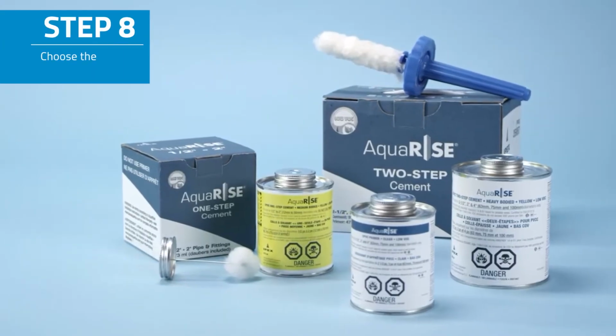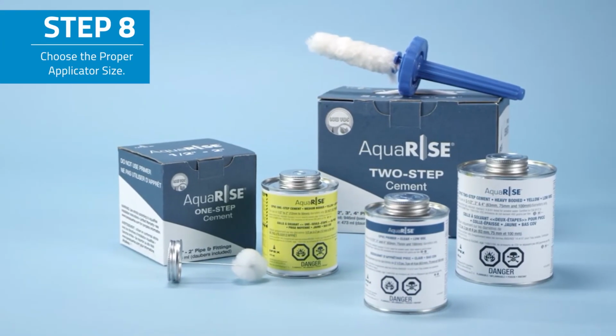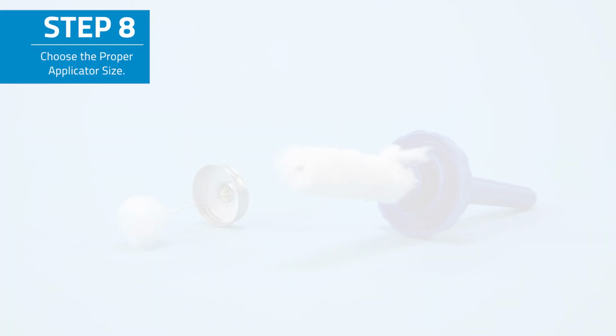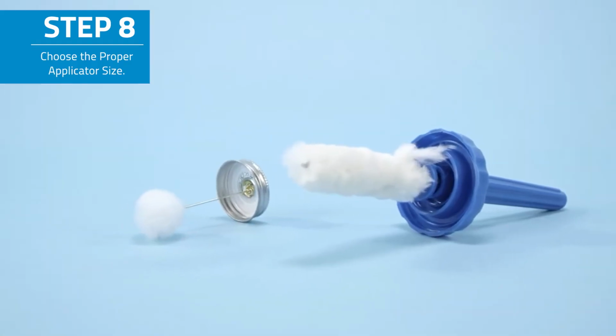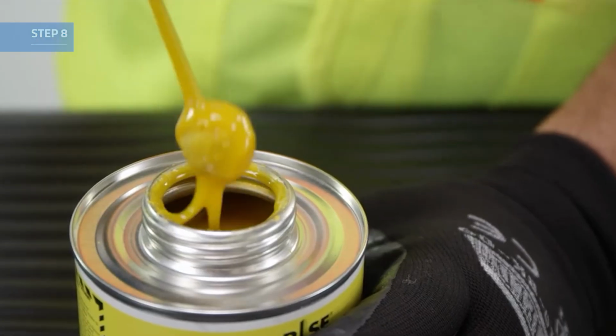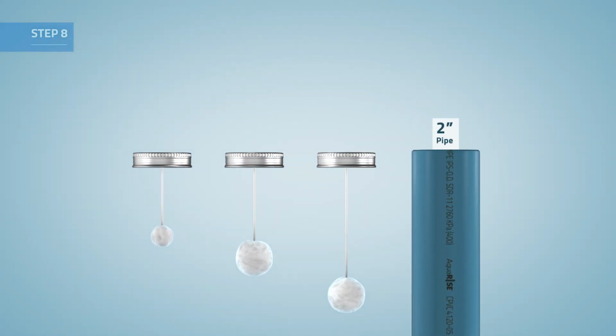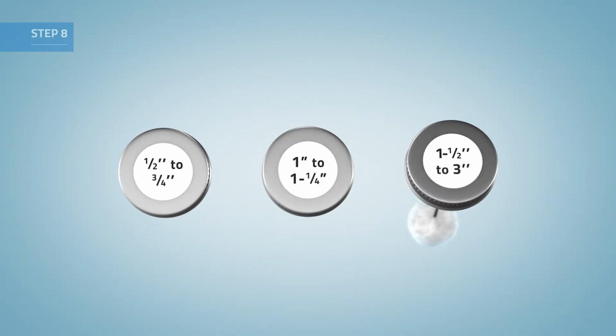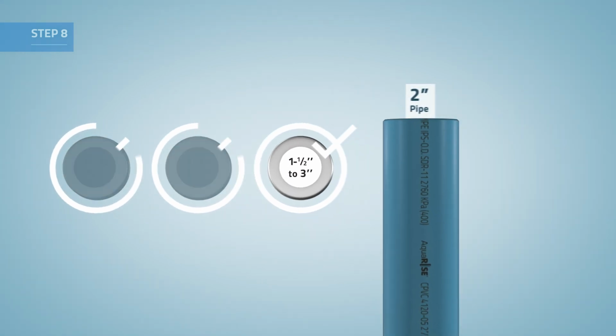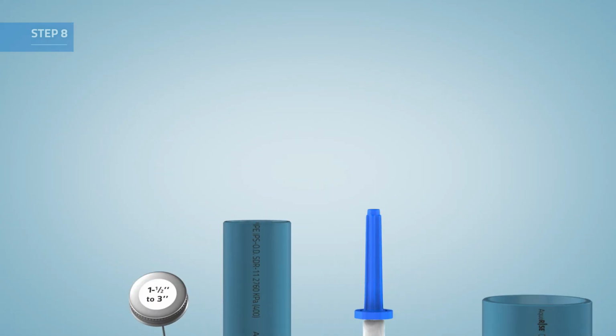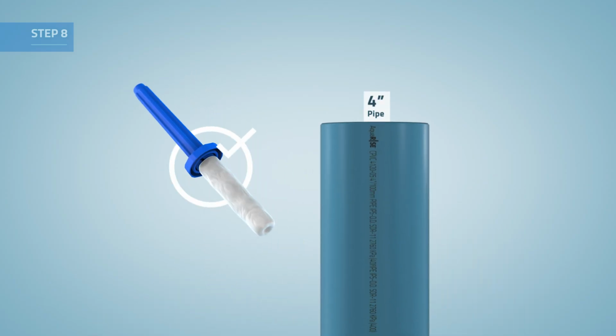Step 8. Proper applicator size is critical for ensuring the correct amount of AquaRise primer and solvent cement is applied. Only use the applicators provided with AquaRise solvent cements. Applicator size varies by pipe diameter. Check the label on the applicator lid to ensure it matches the pipe size you're working with. Super swab is to be used on 4 inch pipe only.